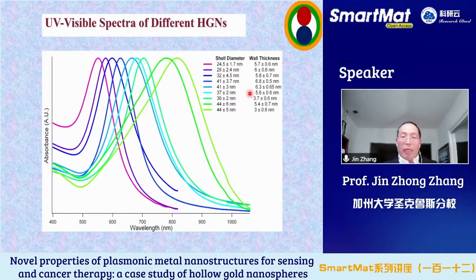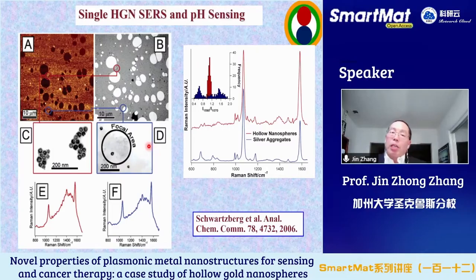Here's the spectrum. You see each sample only has one peak, as I alluded to already. At that time, we didn't understand. We thought there should be two peaks because in the literature, many papers claim two peaks. So we thought there should be two peaks. And we were speculating, maybe the other peak disappeared into the, you know, too blue or too red or something. And today we understand now, actually I understood a few years later when I was writing a review article, if it's a true spherical hollow structure, there should be one peak, because it's completely degenerate in all directions, just like a solid particle.